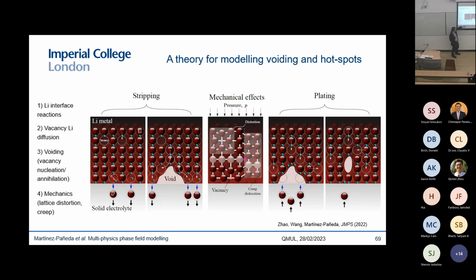Whenever you're doing stripping, you are removing lithium atoms, so that you can capture through a boundary condition. Whenever you have plating, you are depositing lithium atoms in your material. So again, we can use this through a boundary condition. You also have vacancies or substitutional and surface lithium diffusion within the bulk. And this we can capture by solving some sort of transport equation for the lithium coverage. And then, of course, we have the voiding process, which is essentially vacancy nucleation and annihilation. And this is quite important, as I said before, because this is what is going to generate those current hotspots.